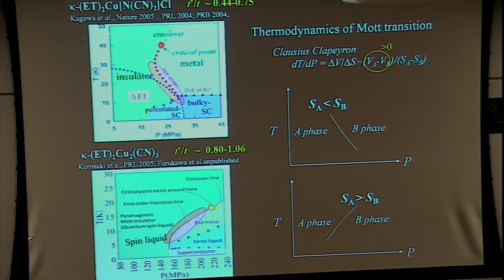But in the antiferromagnetic case, the slope is reversed. Why? This is the antiferromagnetic ordering temperature here. But even at higher temperatures, short-range ordering occurs. This is very clear because near the ordering temperature, there are no specific heat anomalies. This means that the short-range order develops at higher temperatures. So this reversal means that the spin entropy is high at high temperatures because all of the spins are paramagnetic. However, at low temperatures, with short-range order, the spin entropy gradually dies out, and then the entropy of this A phase is smaller than this one, the metallic one. So it's very reasonable.